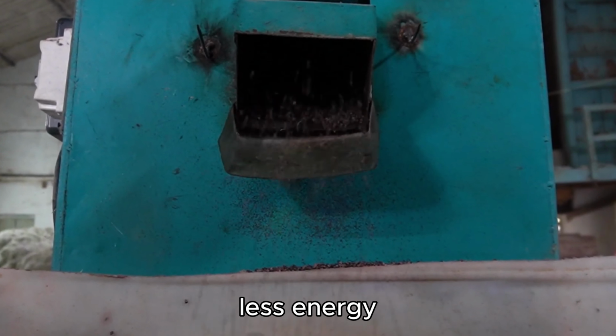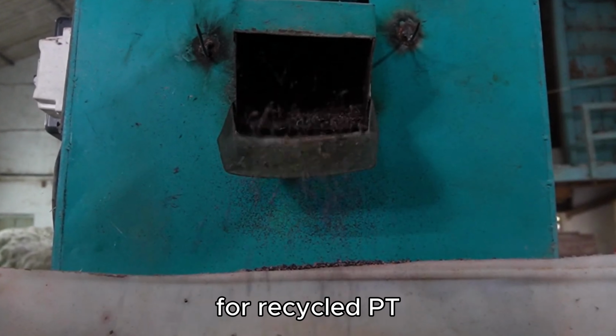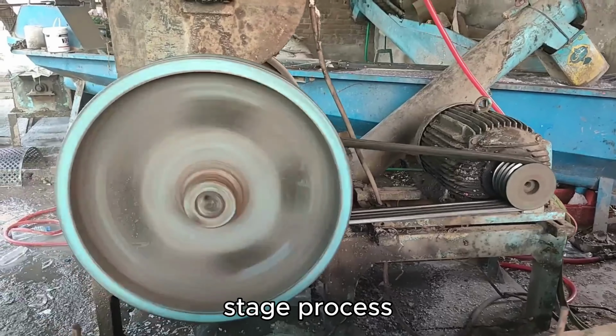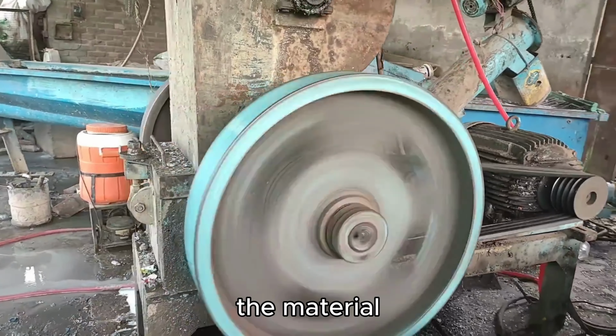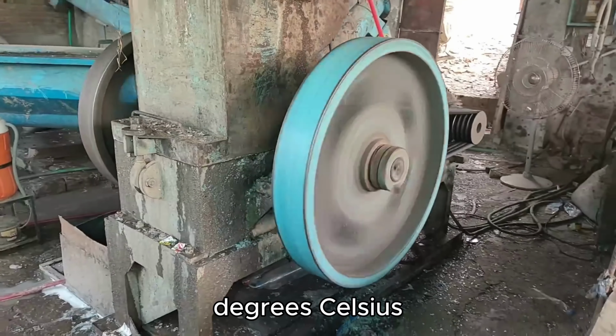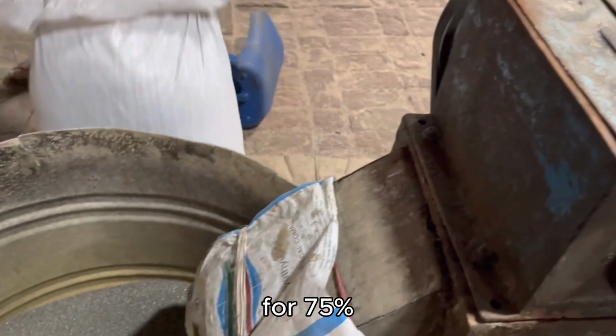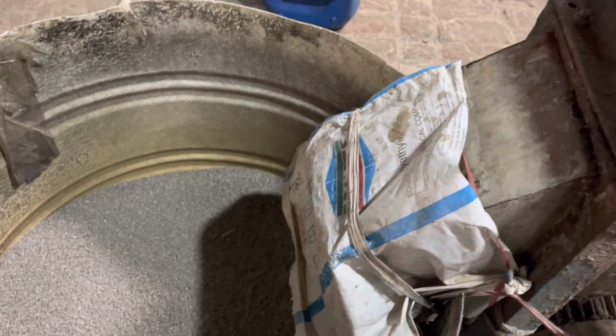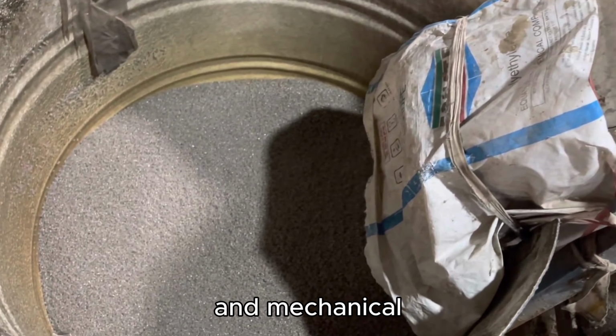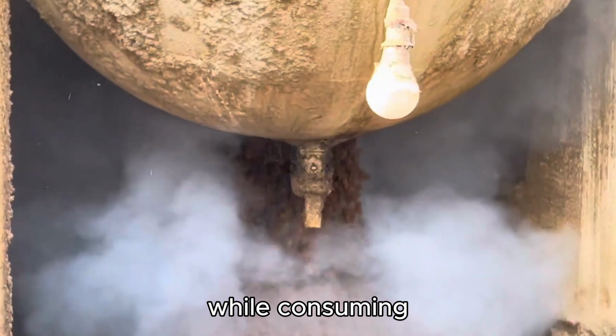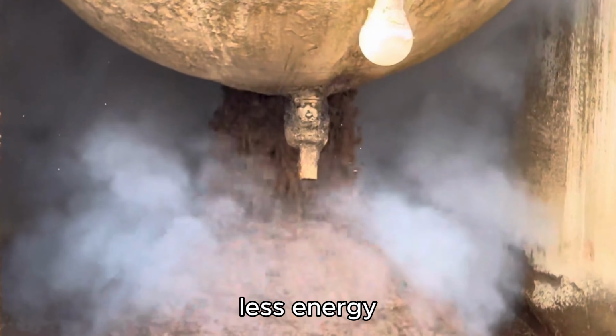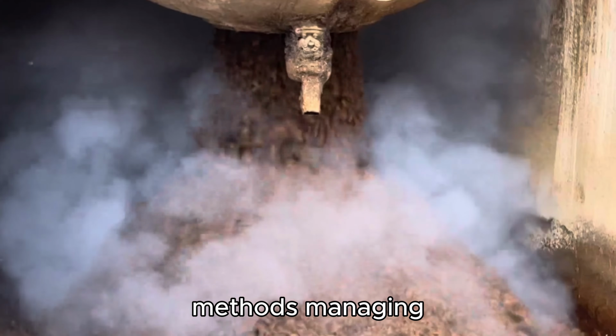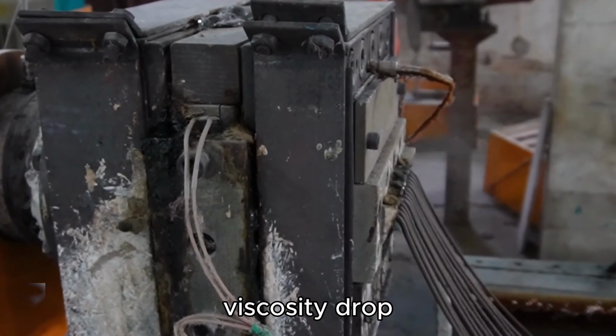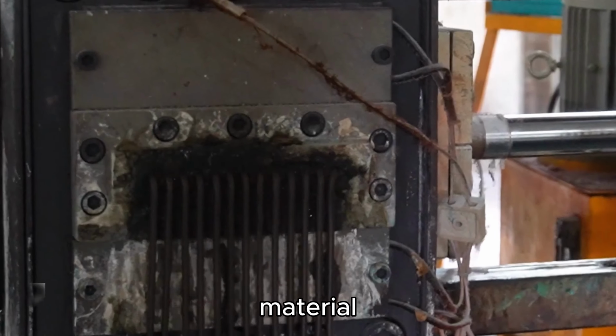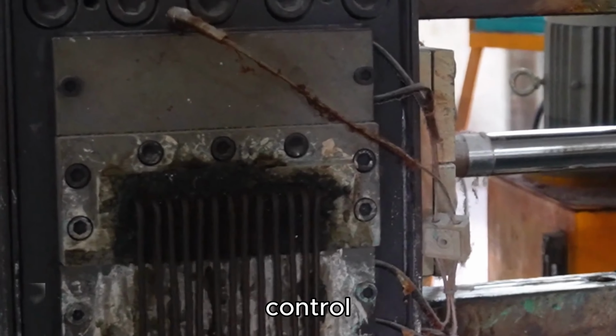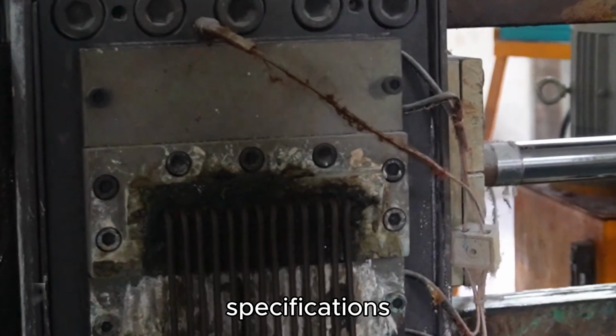Advanced vacuum systems for recycled PET use a precise 4-stage process that keeps the material below 160 degrees Celsius for 75% of the drying cycle. This protects color and mechanical properties while consuming up to 33% less energy than traditional methods. Managing the intrinsic viscosity drop in recycled material requires this precise control to maintain bottle-grade specifications.